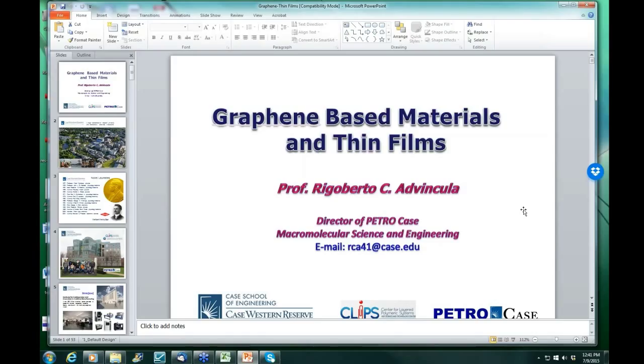Same with graphene. The interesting properties of a graphene composite typically show up when you make very, very thin layers in which the graphene oxide or graphene material is oriented parallel to the surface of the substrate.